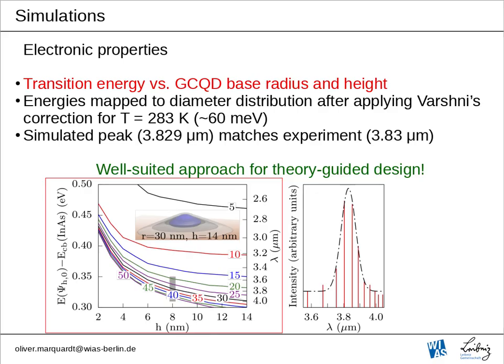Next, we have mapped the energies from our simulations after applying a Varshni correction for T equals 283 Kelvin, which makes about 60 meV, to the diameter distribution we have seen in experiments. So that's essentially the gray bar you see here on the left side, which gives you the systems that were observed in experiment, and we have then mapped this on the corresponding histogram and produced something like a simulated spectrum.